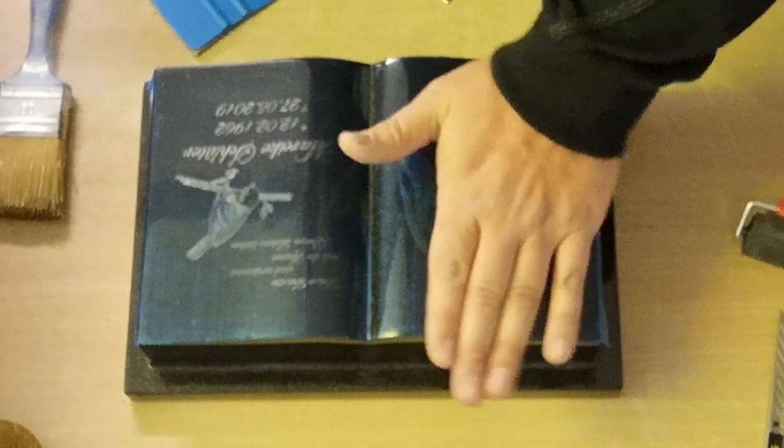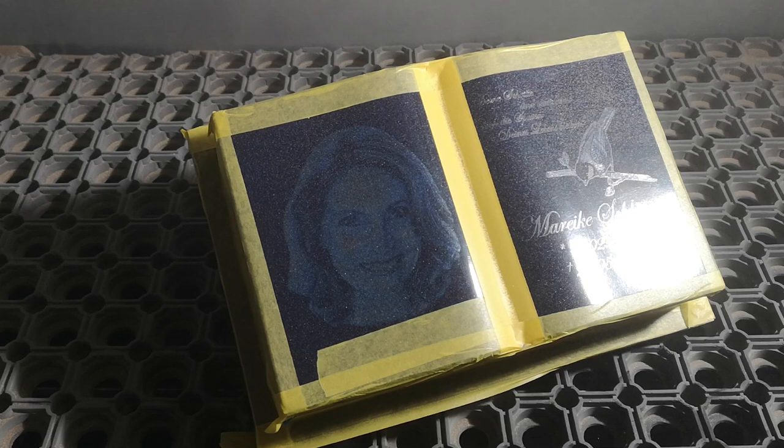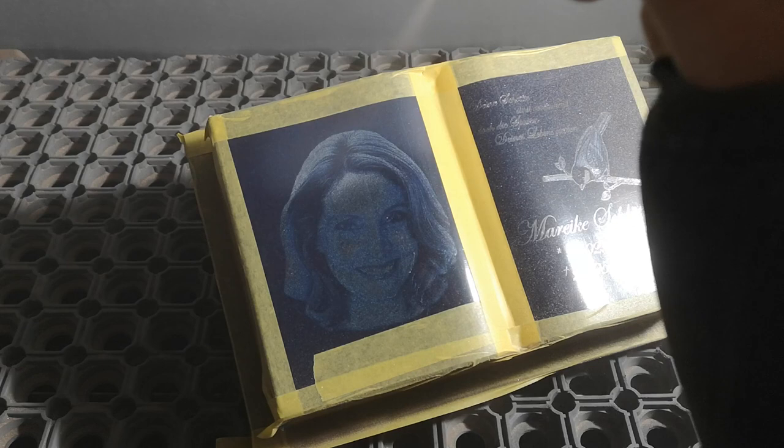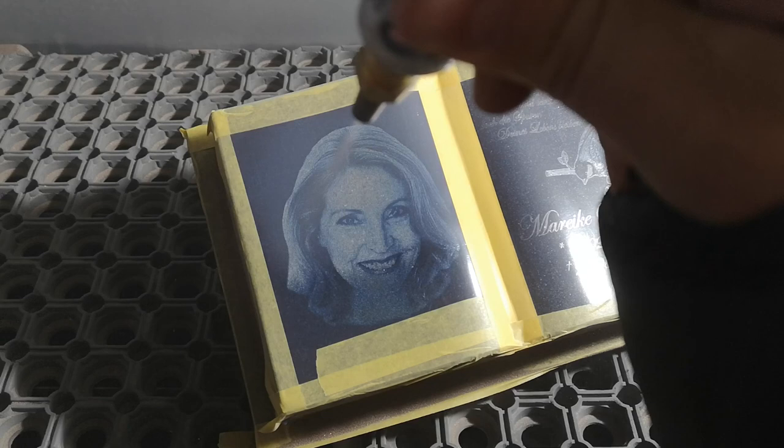So just to remove the air bubbles between the granite and the halftone dots. And now you can see the inside of my sandblasting cabinet. Now I'm using a pressure pot unit with a very fine tip. So it's a carbide nozzle about 2.5mm, so very fine. I'm using aluminum oxide 150 mesh and a pressure of about 30 psi.